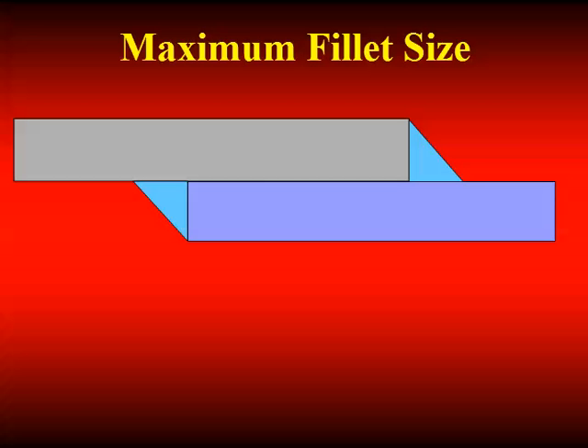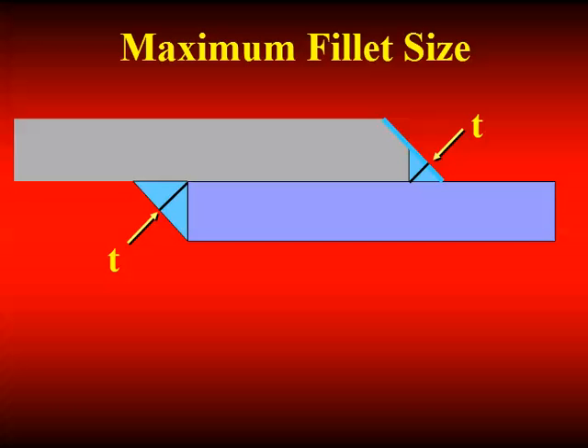And here's the lap joint where the leg size is equal to the thickness of the material. Years ago, welders learned that if they directed the arc to the corner of the steel and melted away that corner and flowed the metal down, when the inspector showed up, it sure looked like a weld was made the full size. But the throat wasn't what people expected it to be. Whereas the designer was expecting this throat, what they were actually getting was that throat. So to preclude that practice, this maximum weld size provision was implemented.